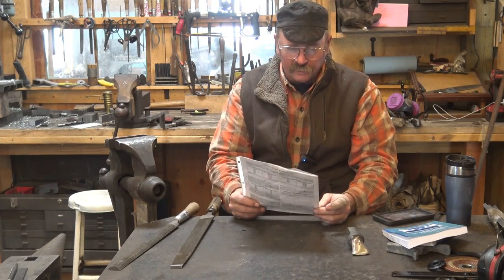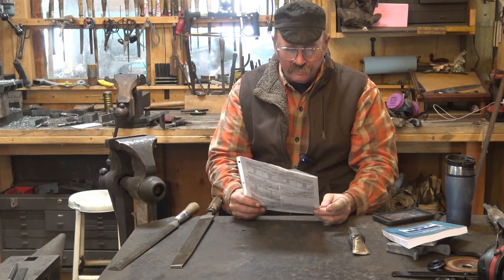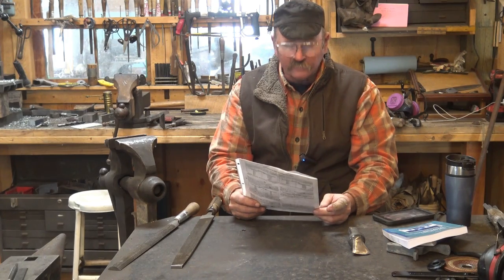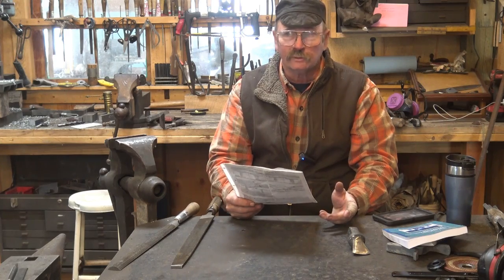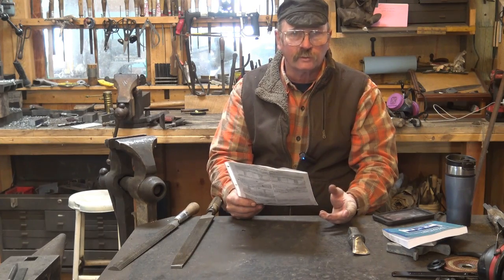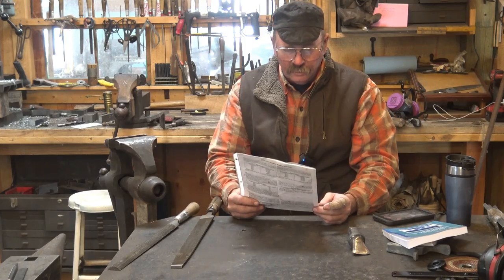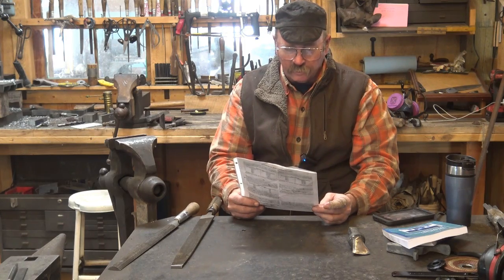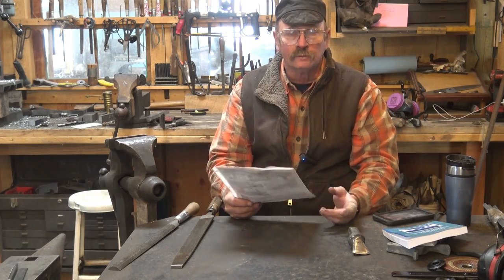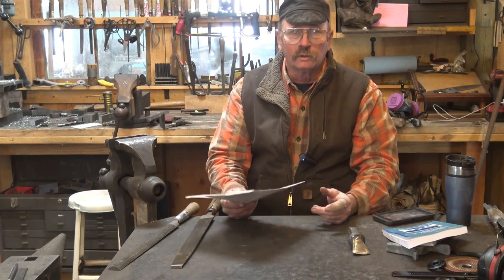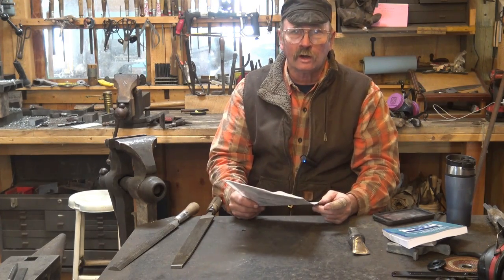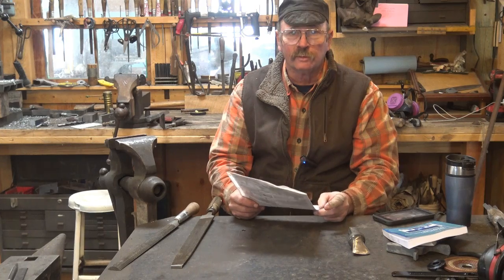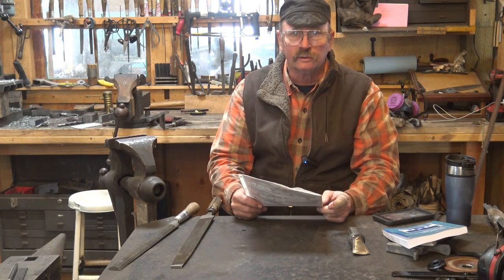And for S2, it says preheat to 1200 degrees, then bring it up to 1550 to 1650, so it tells you exactly, which we can't control perfectly in the forge, we have to go by color, and hold for 5 to 20 minutes, then quench in brine or water. So brine is salt water. So we'll quench in water. We don't need it rock hard, so if water's a little bit mellow on quench, we'll do that.